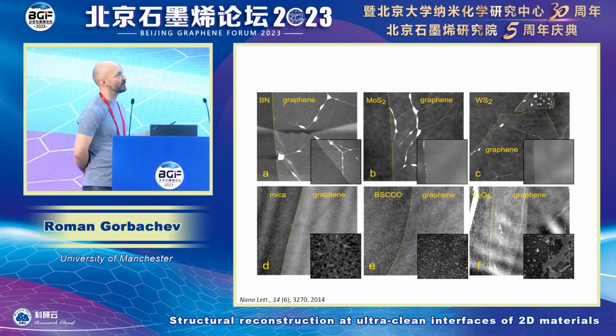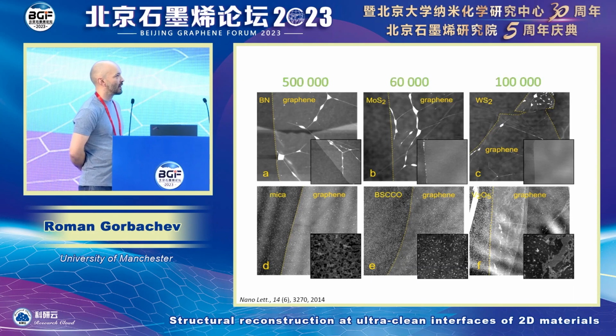But we can do beautiful fundamental science if we only focus on the areas in between, on the clean and nice areas. And so there are also a lot of materials where this kind of cleaning process, self-cleaning, doesn't happen. So you transfer them together and all the contamination that has been trapped in between stays trapped in a continuous layer. A lot of materials like, for example, copper oxide superconductors or mica, they remain relatively unexplored in terms of heterostructures because we simply cannot make them form these beautiful clean interfaces.